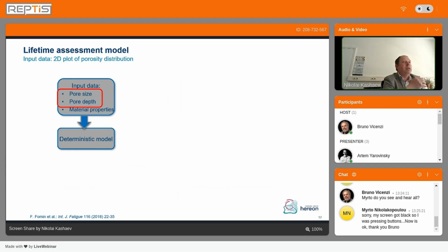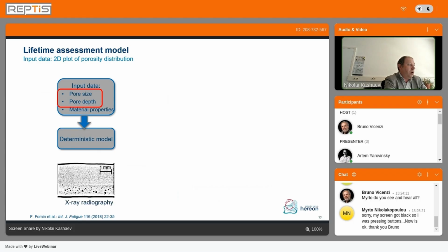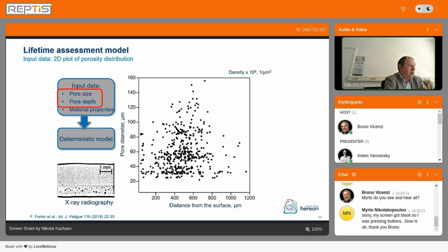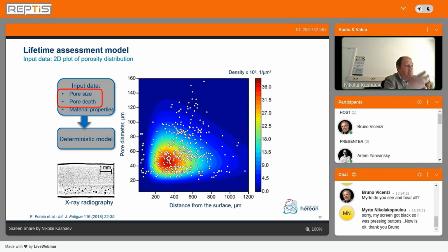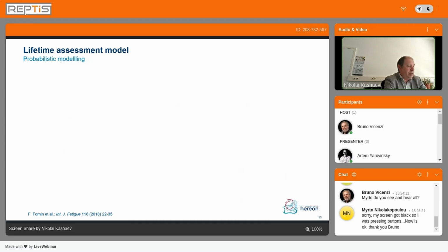For example, if we consider the distribution of defects, such as pores, with regard to their size and, for example, the distance to the surface, the pore depth. How can we do it? We can do, for example, X-ray radiography. Here is an example of a welded seam. And by analyzing the results of X-ray radiography, we can represent the distribution of pores with regard to their diameter and distance from the surface. And then we can mathematically describe the distribution. And now the color corresponds to our density distribution. And we can work with this approach.